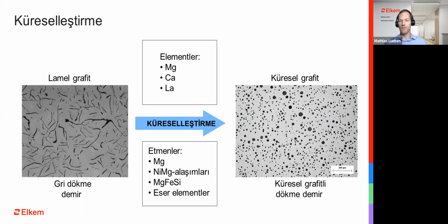The treatment alloy must be chosen adapted to the specific process. For example, to understand some influences, a too high magnesium content results in an increased reactivity and reduced magnesium yield. Calcium, on the other hand, reduces reactivity, ties up sulfur and oxygen, and will give an inoculation effect. Calcium increases the magnesium recovery and the tendency to slag formation. Rare earth, on the other hand, ties up sulfur and oxygen and nodularizes the graphite. It neutralizes the subversive elements, reduces reactivity, and gives some inoculation effect. And finally, the use of lanthanum instead can reduce chill and shrinkage tendency.